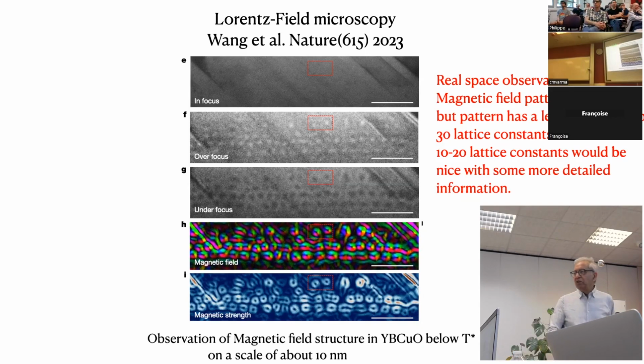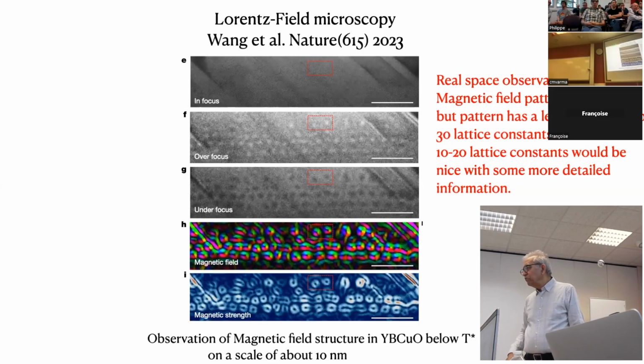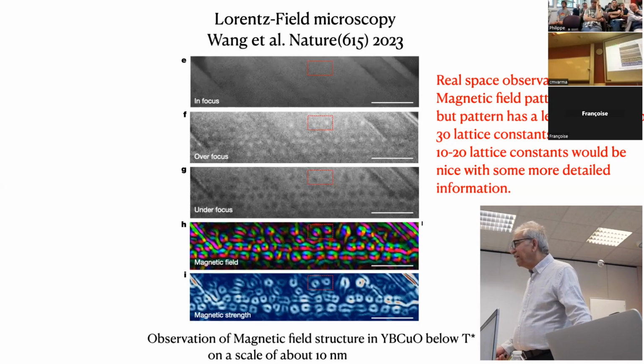And they find, when they have to invert this thing, calculations. That's the most terrible thing, right? You do an experiment, you should directly say, here they have to do a calculation, and they have come up with this pattern, which is some magnetic field pattern, like a magnetic field which is changing directions in the plane. They only look at that, and this length scale is of order 200 angstroms, okay? Whereas I would like it to be 50 angstroms at most.